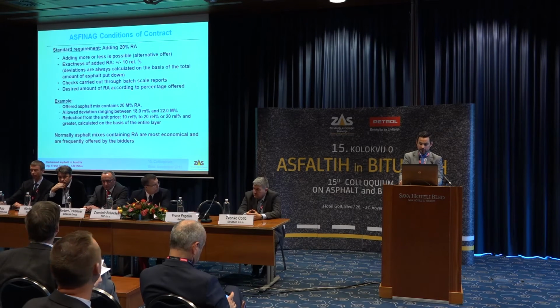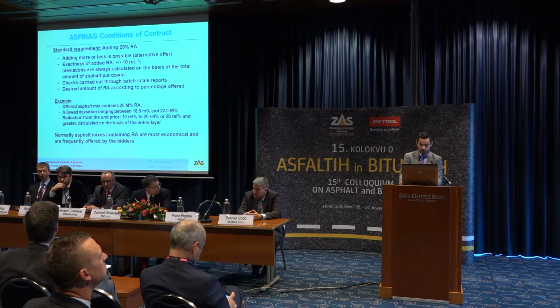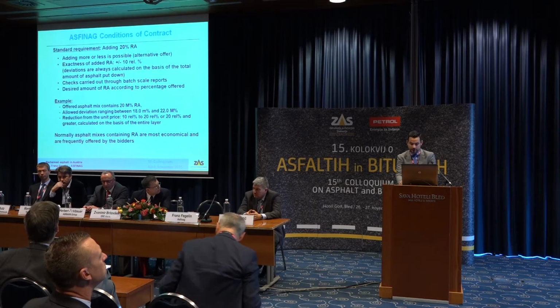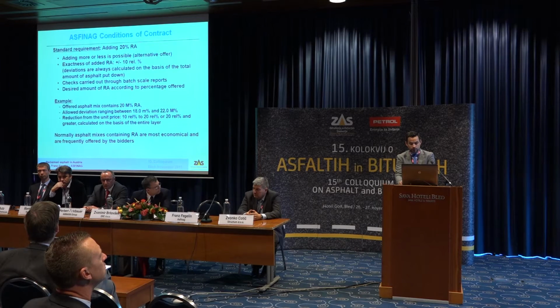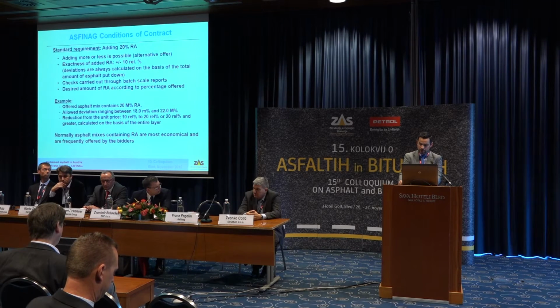Currently, the Asfinag standard tender documents include the following regulations. The service description includes the requirement for the aggregates containing 20% recycling asphalt. The adding of more or less is always possible, but it has to be submitted as an alternative offer. The exactness in terms of added recycling asphalt is plus minus 10%, related to the total amount of asphalt in place, and is regularly checked by means of batch reports. The desired amount of recycling asphalt to be added is related to the penalty payment calculations.